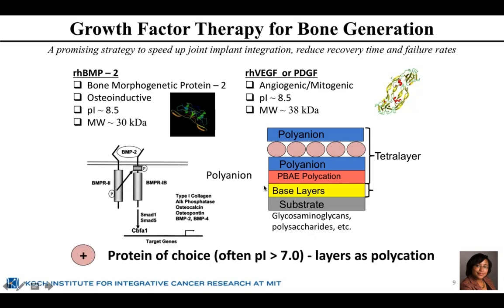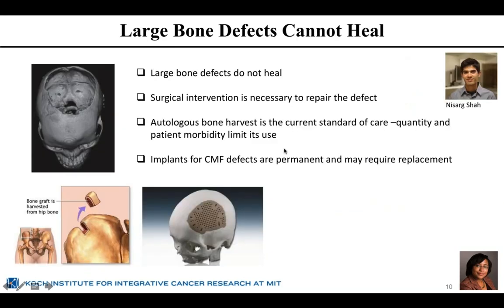And in that film, we have essentially a polycation that degrades, like the ones I showed you before, poly-beta amino esters, a polyanion, which can be polyacrylic acid, or polysaccharides or glycosaminoglycans that are negatively charged. And we have our protein sandwiched between that polyanion.